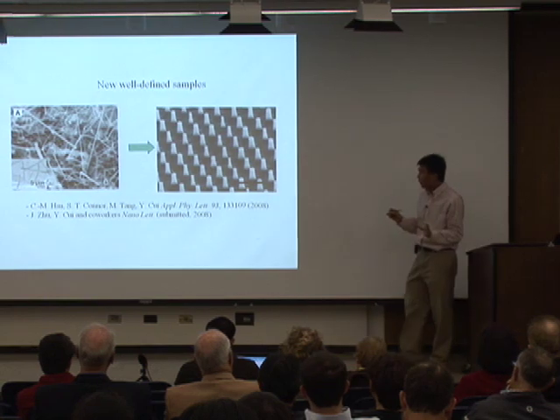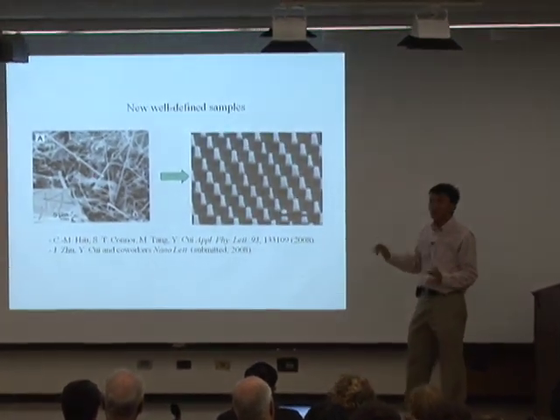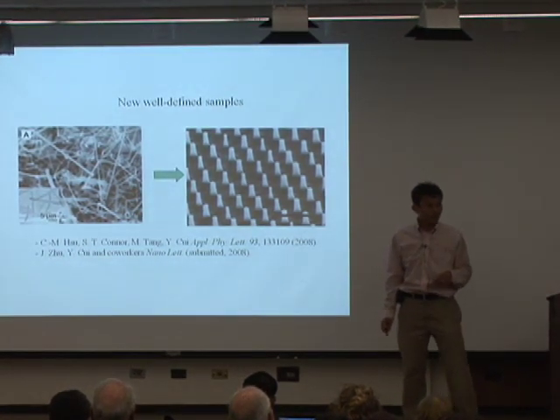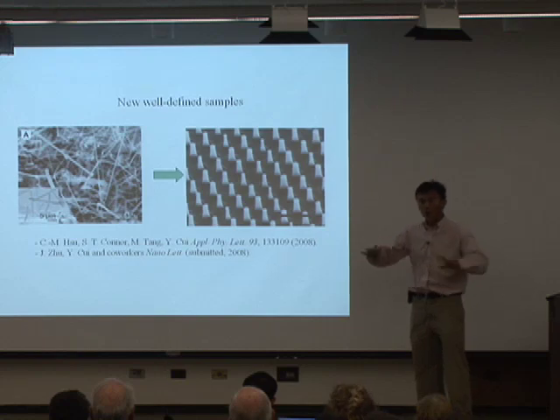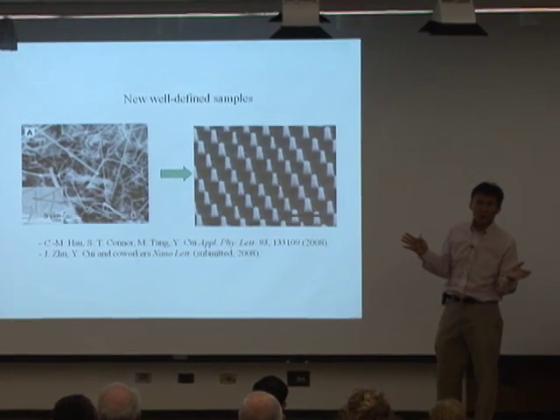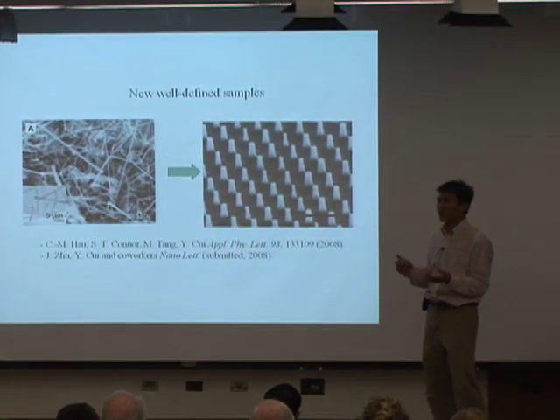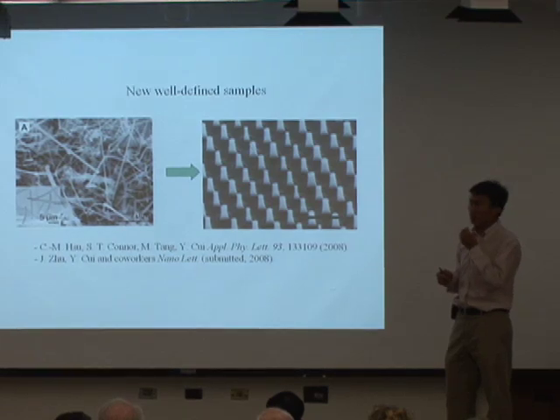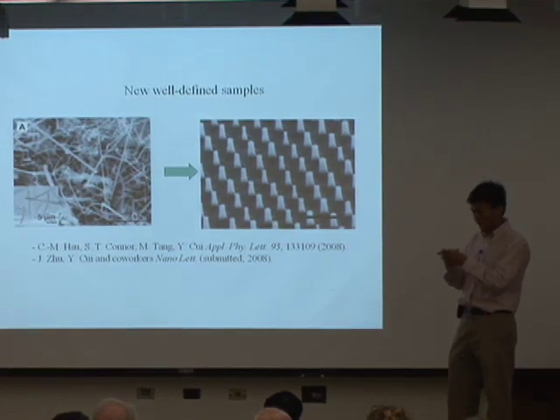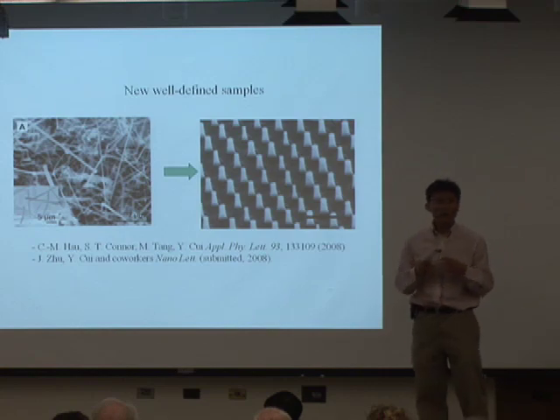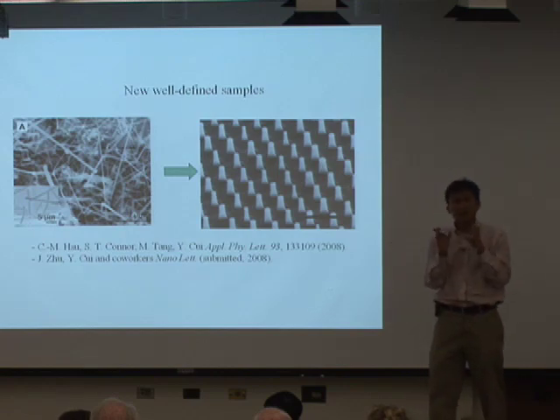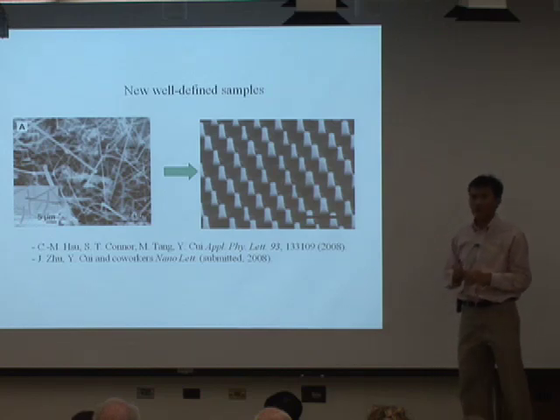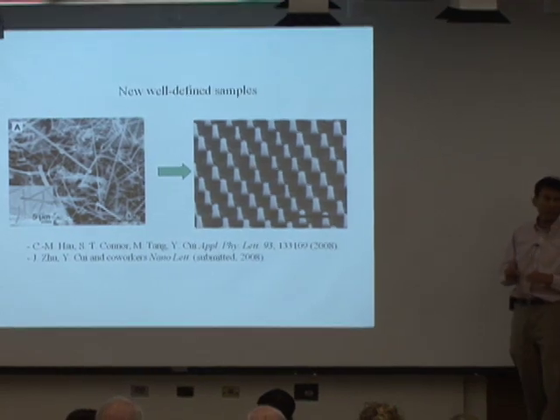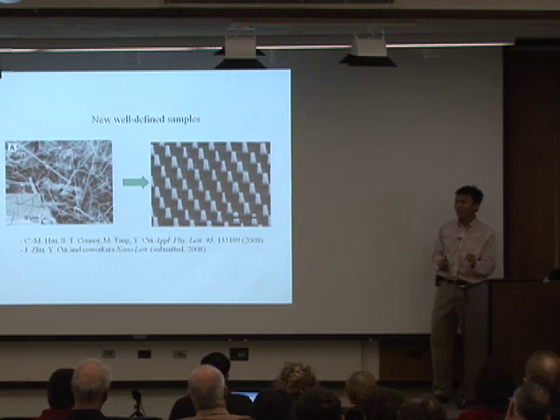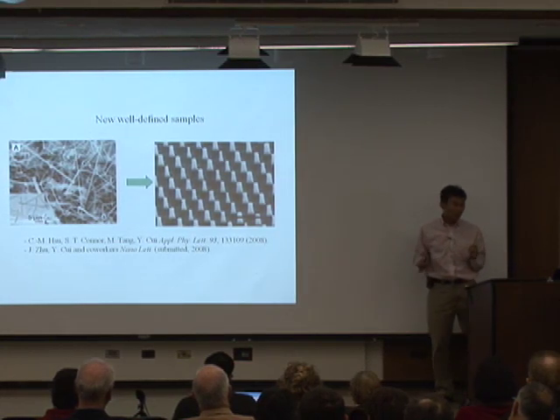So we are interested in new well-defined samples. Well, this was the TEM picture I just showed you, 10, 20 slides ago. So we made this nanowire. They are randomly oriented. Nothing wrong with this nanowire. They are nanowires usable for batteries. But for fundamental understanding, given a certain amount of lithium going in, you want to see how much volume change you have, and you would like to see whether there's a breaking at the interface between nanowire and the metal electrode. Well, that's harder to do. This looks very messy. So what we like to have is this type of pillar. So each nanowire you can watch clearly. You make them into the same size. So that motivates us